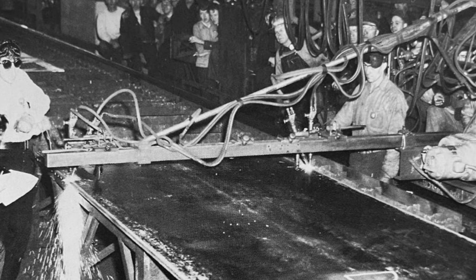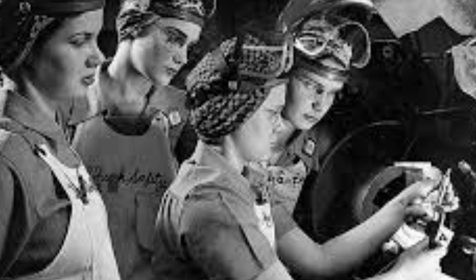At room temperature, the steel could bend and flex, absorbing enormous amounts of energy before failing. But in the frigid waters of the North Atlantic, that same steel became as fragile as glass. Tipper's discovery explained the physics of the failures, but it revealed an even deeper problem. In a riveted ship, if a crack started, it would run until it hit a joint between plates. The overlapping plates would stop the fracture, containing the damage.